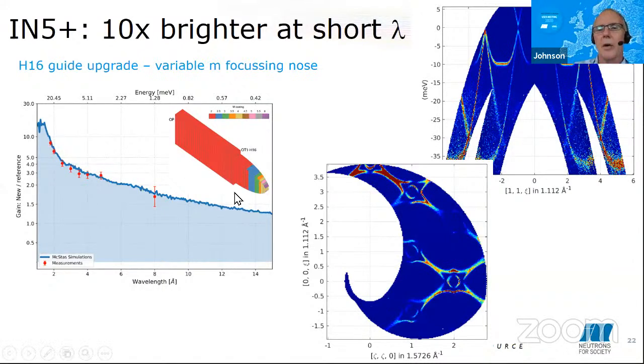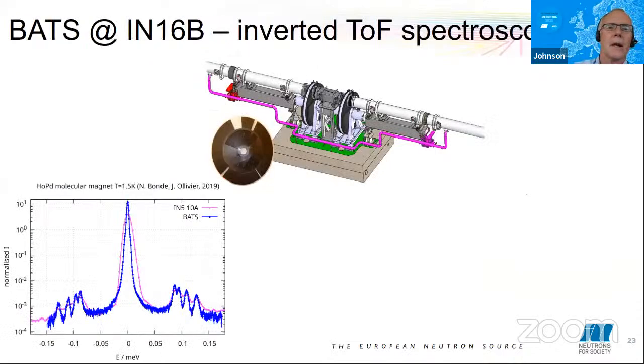And so that will facilitate the type of measurements you see on the right here, and in particular going out to higher energy transfer in neutron energy loss. With IN5, you can push it to longer wavelengths to improve the energy resolution, but then you run into the essentially the dynamic range of IN16, which is a backscattering spectrometer.